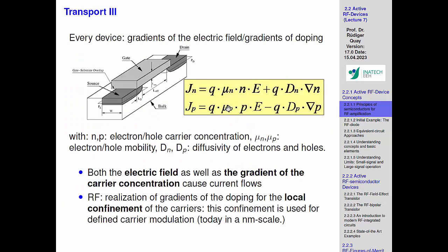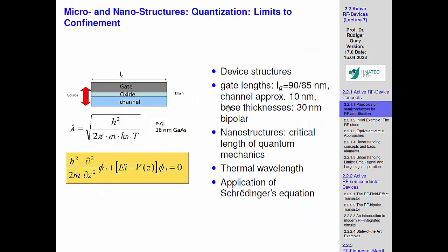And I want to point out one fact. We have this very strange idea about a gate. And when the electron behaves as a wave, then something very fundamental starts to be tricky. So we have that strange idea that there's a source, a drain, controlled by a gate. You learned that field effect, modulation of the gate controls the current between source and drain. That's a MOSFET. The trouble is, this effect starts to vanish the moment when you are going in the direction, or to be precise, on the size of this wavelength. So if the object which you're seeing is smaller than the wavelength, then suddenly this idea that you control the source to drain current by the gate doesn't work anymore, because the electron traveling from source to drain simply doesn't see the gate anymore.